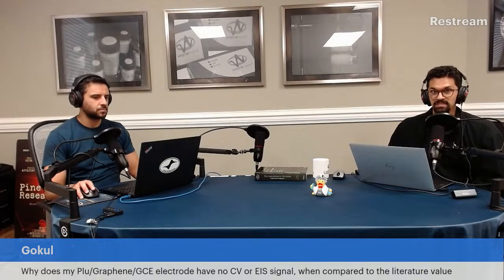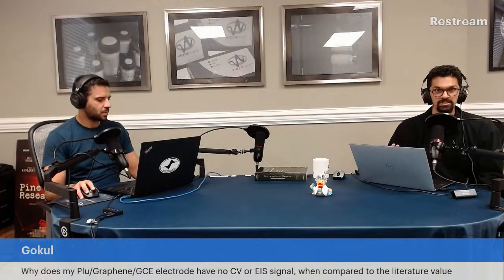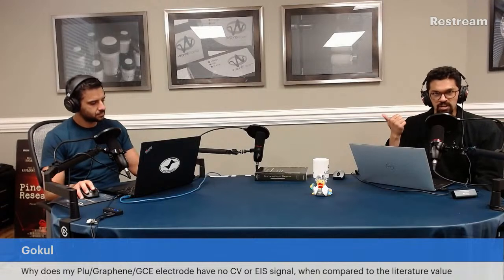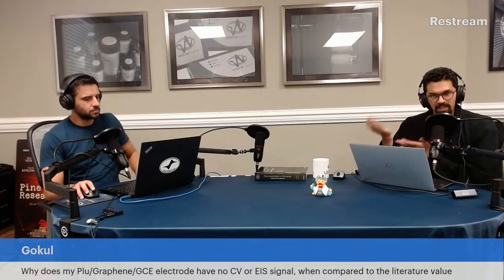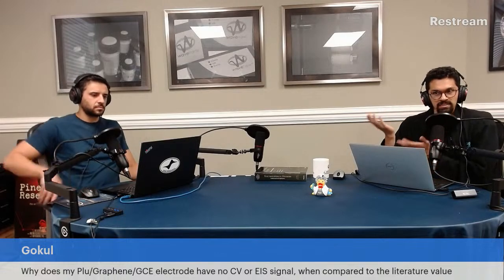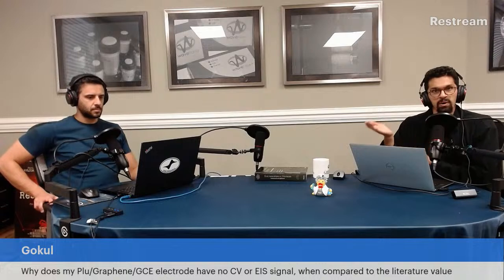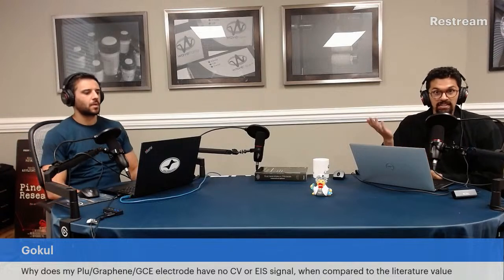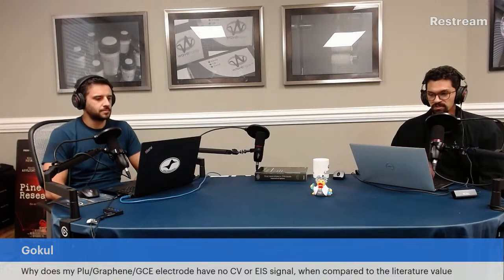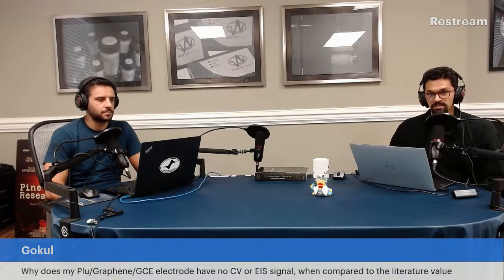It's blocking. It's actually insulating. That's my first impression, just based on looking at a glassy carbon electrode and then glassy carbon with graphene. And then when you add the polymer, I think it's actually insulating. There's something wrong with the polymer because you're not getting any current response for a somewhat well characterized system.